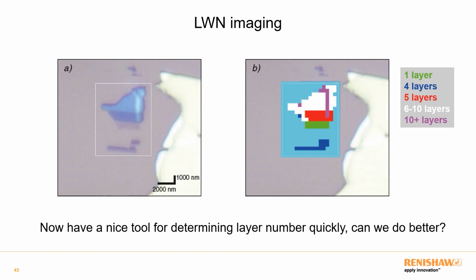Here I've moved to a different flake, and you can see the flake's quite small. I've conducted a simple Raman map across the flake, collecting around 250 points in about 10 minutes. I'm able to very quickly, using DCLS, direct classical least squares, determine how thick each of these regions is. We can see we've got a 1-layer region, a 4-layer region, a 5-layer region, a region where we have between 6 and 10 layers, and a region where we have 10 plus layers.